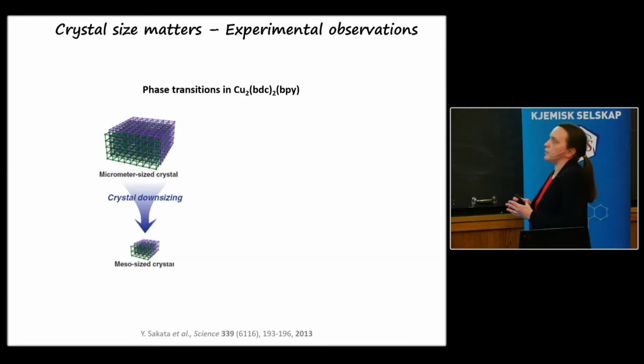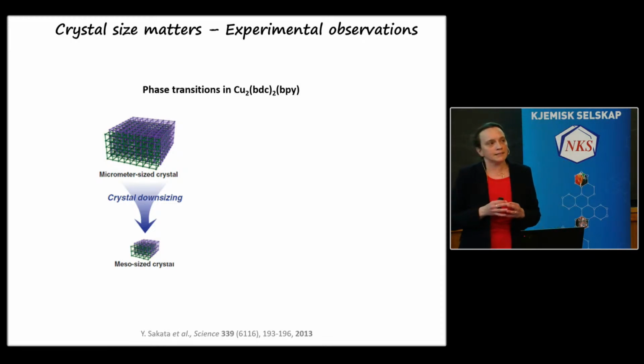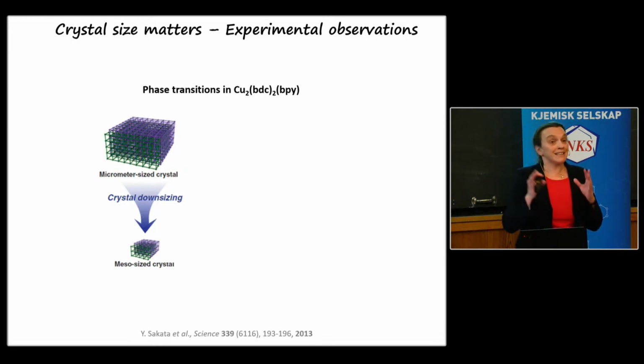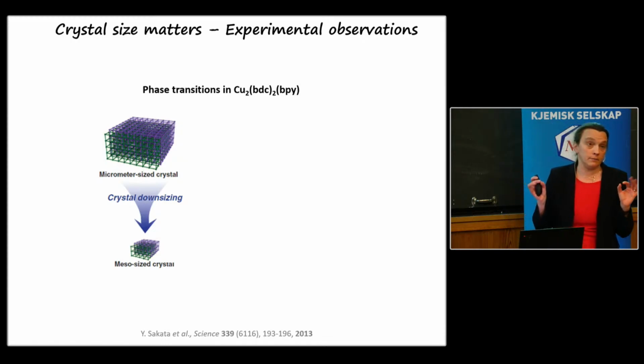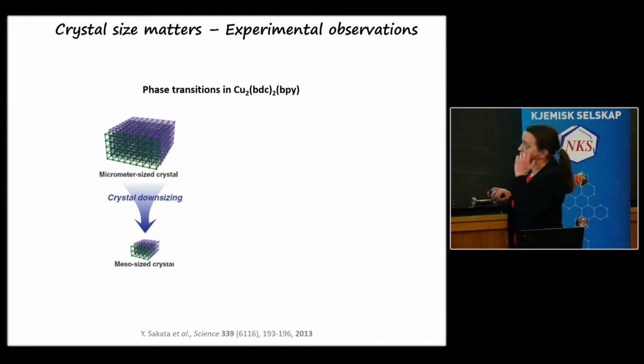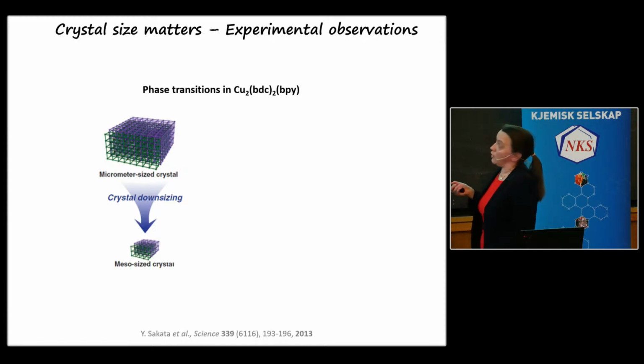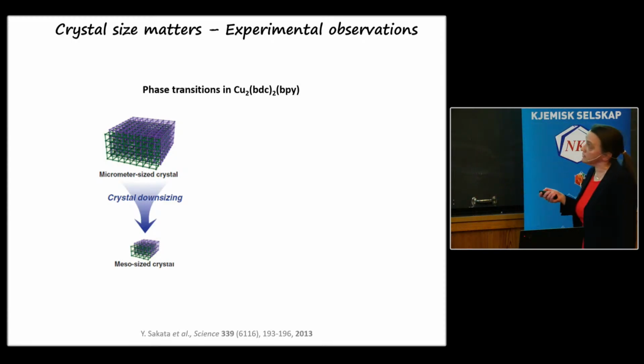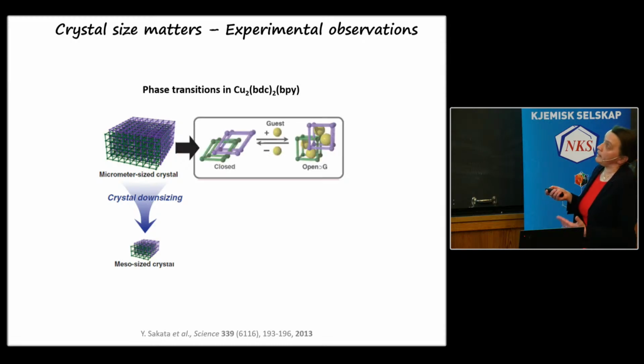That is all interesting, but experimentally it was also observed that this behavior that I explained now is critically dependent on the crystal size. One of the earliest reports that showed this was this paper that appeared in Science. So basically, we start here from this material which has micrometer-sized crystals. What they see is, they start in the closed pore phase. They do gas adsorption. The material opens. But then when you remove the gas, the material closes again. So you have reversible behavior.